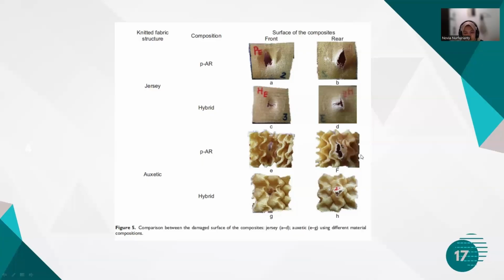For the para-aramid composite, regardless of the weft knit structure, the tear dimension was greater than in the hybrid composite. The image shows a favored direction of failure, indicating an elongation in the front and rear side. According to the literature, elongated failures following the fiber directions are associated with fiber-matrix interface rupture and subsequent delamination. In this study, delamination does not occur, but probably the use of the para-aramid yarn increased the influence of the rupture of the fiber matrix.